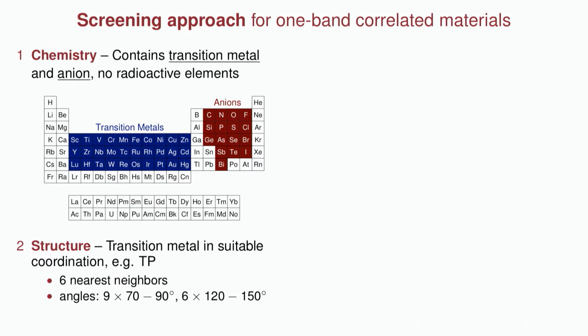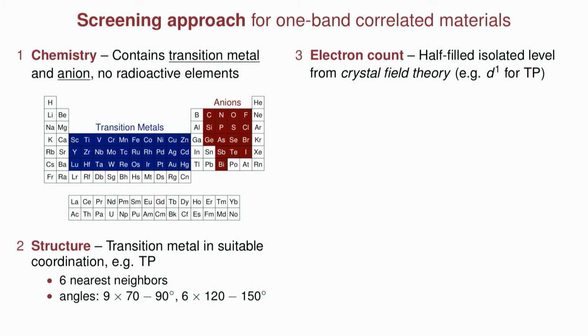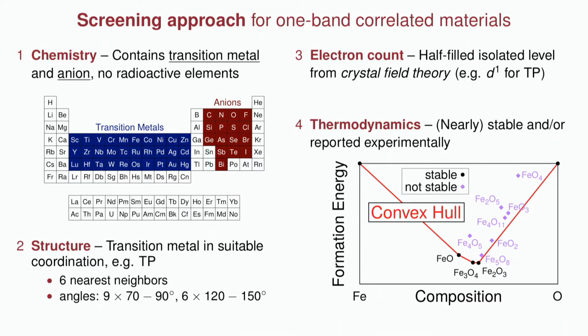For each of these suitable coordinations, we also want to consider the nominal d electron count on the transition metal such that we can achieve this half-filled isolated level from crystal field theory. So for example, for that trigonal prismatic phase, based on that splitting, we just wanted a d1 system, or 1 d electron on that transition metal. And finally, we consider explicitly the thermodynamics. So in thermodynamics, the stable compounds are the ones whose formation energy as a function of composition sits on this geometric construction called a convex hull. It just means there's no other linear combination of phases that can lower the energy. So we consider any compound that's on the convex hull. We also, if it's pretty close to the convex hull, we call it metastable. And additionally, to be practical, if there's something that's not too close to the convex hull, but it's been reported experimentally, we're still going to consider that because someone's made it before.